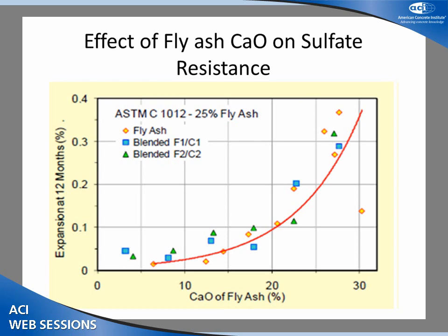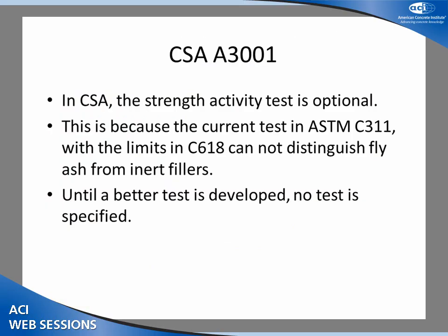But you start to see the sulfate resistance deteriorate at a given amount of ash, because you've got things like tricalcium aluminate in some of these high calcium ashes. You've got other phases in there that may contribute to sulfate attack. It may actually be detrimental at a given level of ash replacement. So the calcium content is where we are in the Canadian standard with respect to those two durability issues. And that's why we picked calcium as the indicator.